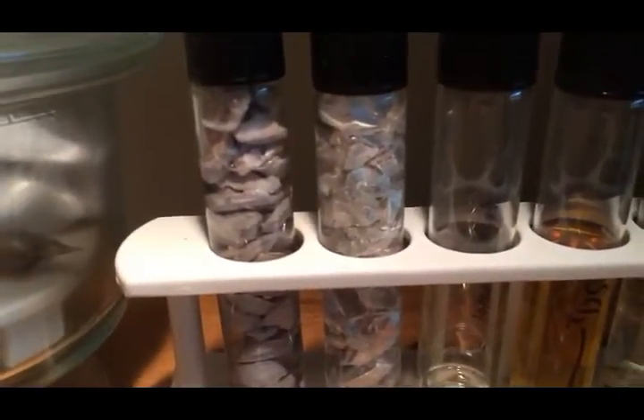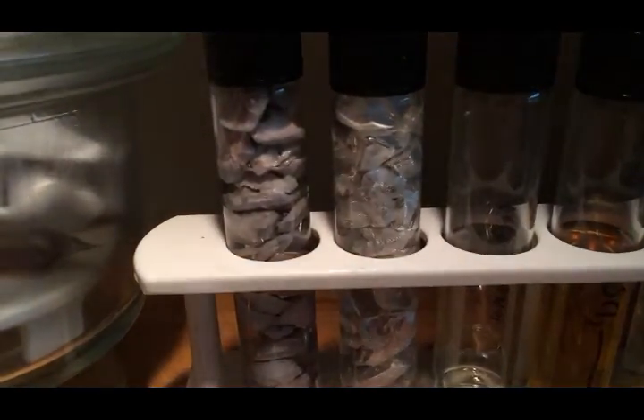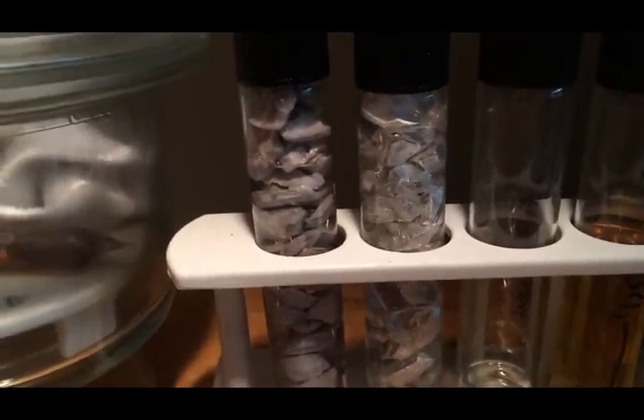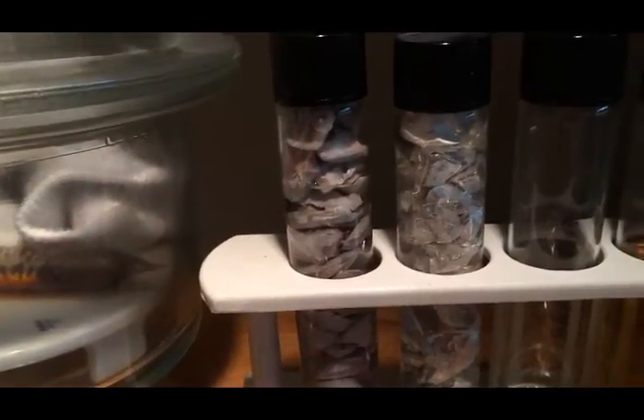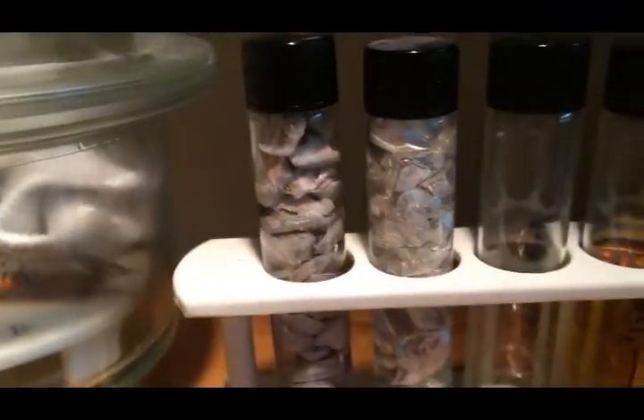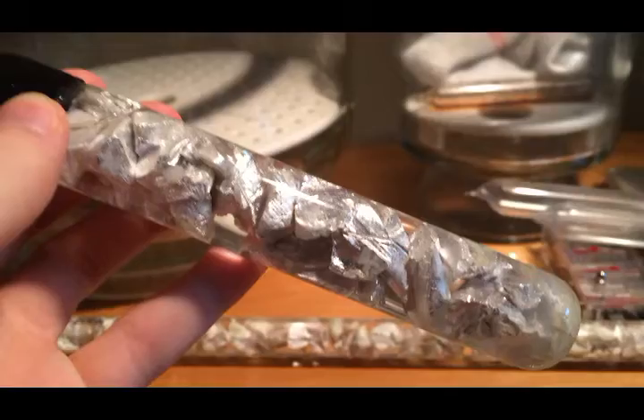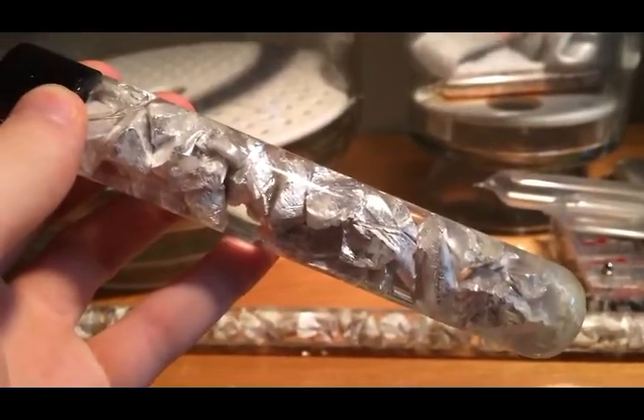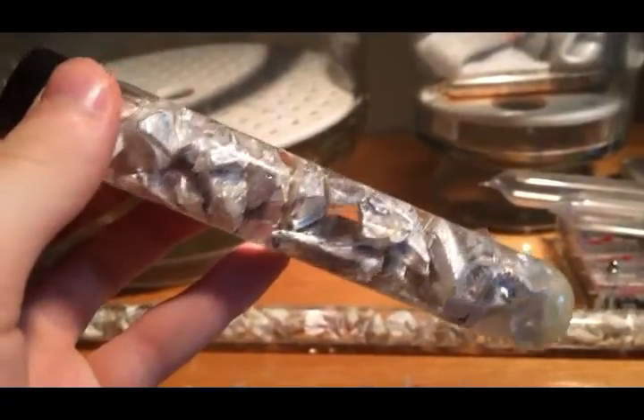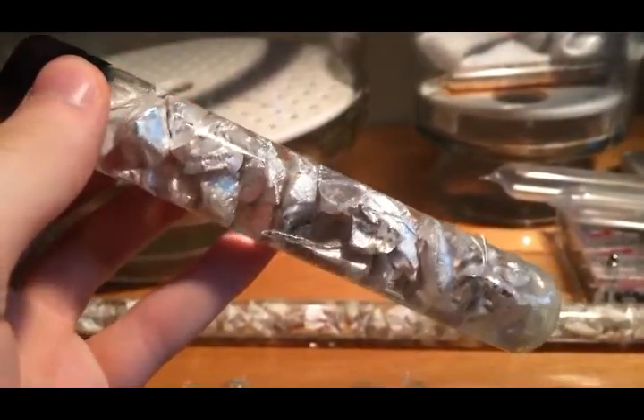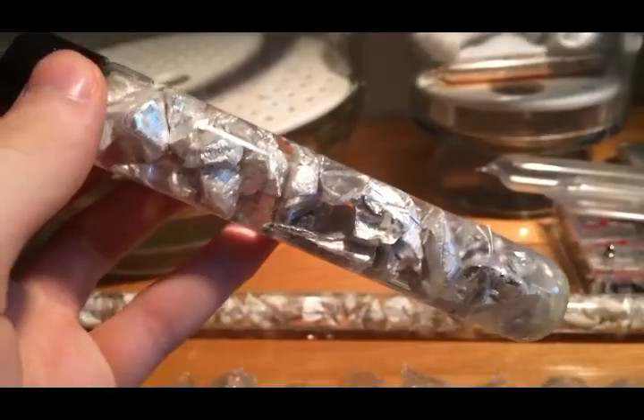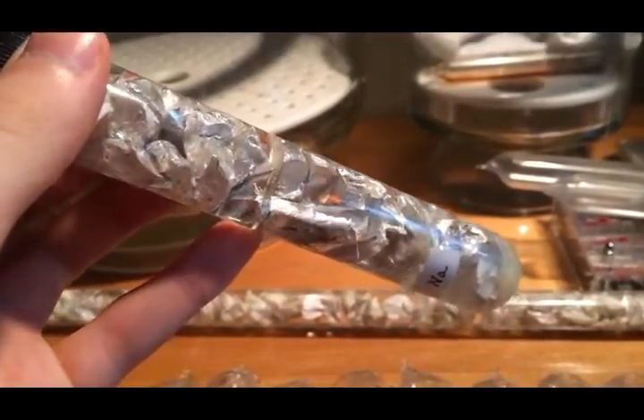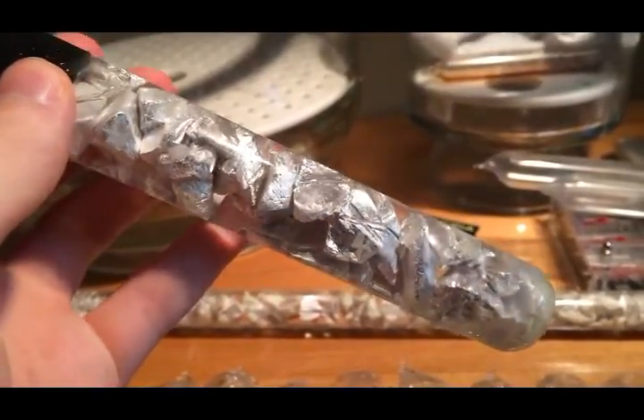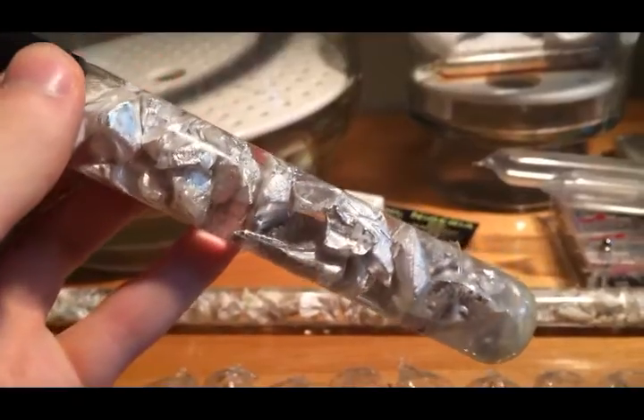The two that I'm focusing on right now are more sodium metal. The one on the left looks basically the same as the other sodium that I showed you, but the one on the right I'm going to take out and get a better view of, because there's something unusual about it. Typically when I seal sodium in a vial, it at least forms an oxide coating as it consumes the residual oxygen inside the container. But for some reason, for more than 2 years now, the sodium has not tarnished.